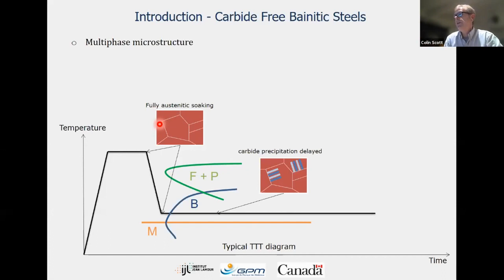These temperatures that we're using are, as you'll see later on, very low, between 375 and 430 degrees C. These are too low for vanadium precipitation. So all the vanadium I'm talking about in this presentation is going to be in solid solution, all of the effects.